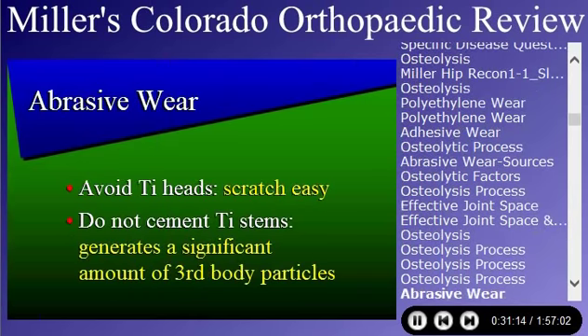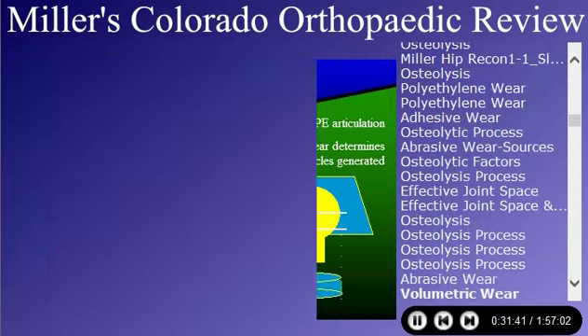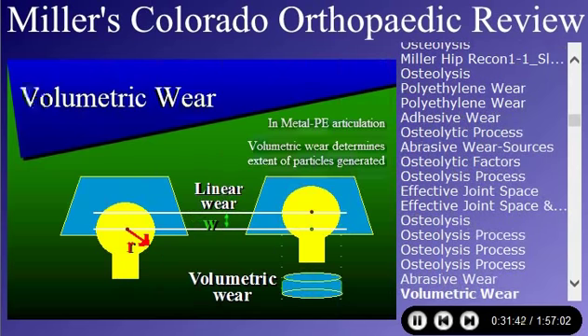What we do know also, in terms of generating debris, is you want to avoid titanium heads. They tend to scratch easily, and that creates abrasive wear, generating a lot more particles. So you don't want to use titanium heads, and you don't want to use cemented titanium stems, because with cantilever rotation and bending, you generate titanium particles which get into the system and scratch the head and then scratch the cup. So avoid titanium heads and do not cement titanium stems because they scratch real easy.